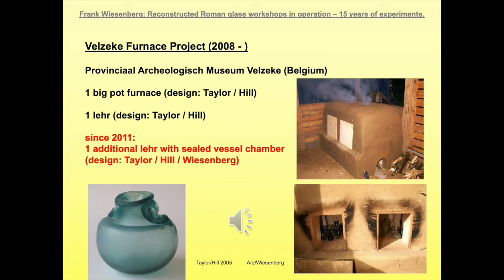The old lehrs seem to cause some kind of dulling of the surface of a couple of glass vessels. It was decided in 2011 to build an additional lehr with a sealed vessel chamber to try to cut down on this effect. This effect is noticeable on the Aryballos depicted on the left-hand side. The sealed vessel chamber, which prevents the hot exhaust gases of the fire from attacking the surface of the glass, works pretty nicely when it comes to delivering a nice surface, but it's pretty hard to operate since the relation between the fire chamber and the vessel chamber is not perfect.